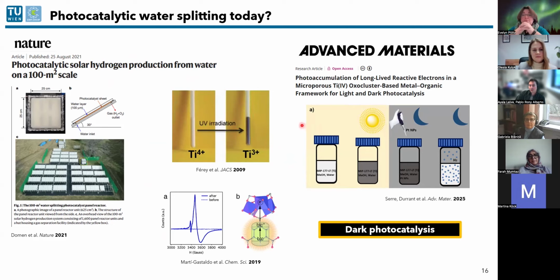But I think here MOFs might be really superior. If you remember, we had this effect where we are accumulating charges in the materials. So we have this titanium 4 to titanium 3 transition, and this has been leveraged to do what is known as dark photocatalysis. The concept is the following: you charge your material with sunlight during the day, and then your material is charged indefinitely. Then, during the night, or whenever you want it to happen, you add some stimuli, in this case platinum nanoparticles, and then you have hydrogen on demand whenever you want it.